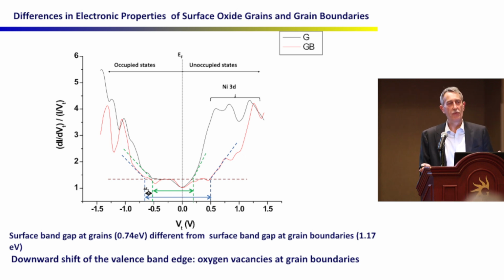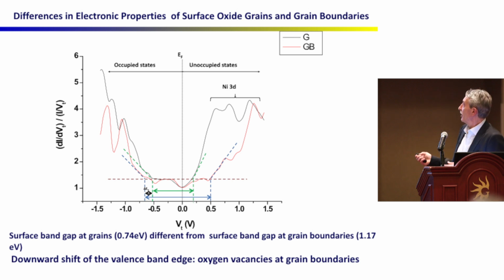So we have a full picture of the electronic structure, and we can distinguish the electronic structure at grains, which is the average of many measurements on top of grains, and at grain boundaries, which is the average of fewer measurements, obviously, because there are fewer grain boundaries than grains on the same surface. We have these two families of curves, and you see that we can measure the band gap, the surface band gap, and that's the one which is important for electron transfers at the solid-liquid interface. We can also measure the position of the upper edge of the valence band, and you can see that there is a shift here.